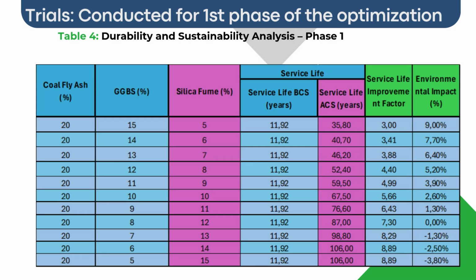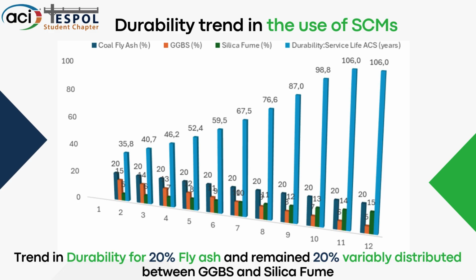This combination allowed an improvement in durability thanks to the action of the silica fume, which reacts with the calcium hydroxide produced during cement hydration. This forms calcium silicate hydrate, which densified the concrete's microstructure and increased its resistance to aggressive agents. As seen in the graph, by increasing the silica fume percentage, the concrete's useful life reached up to 106 years. The result represents an improvement over the base case.